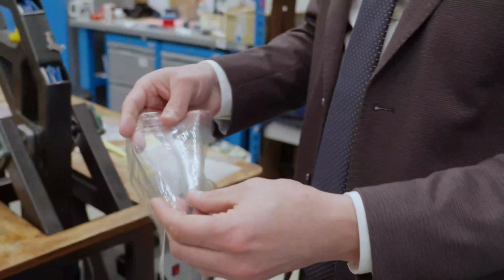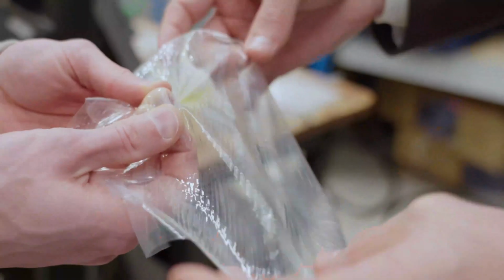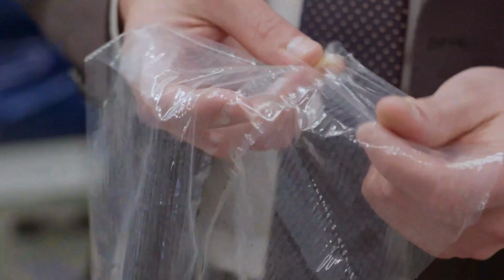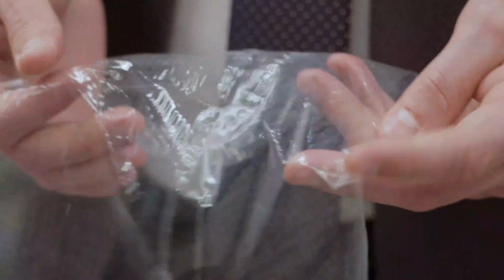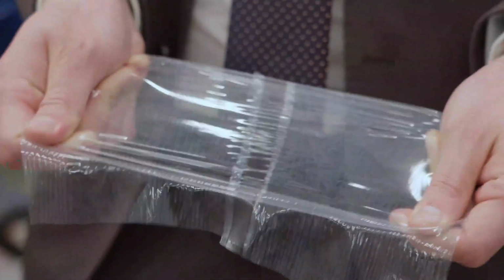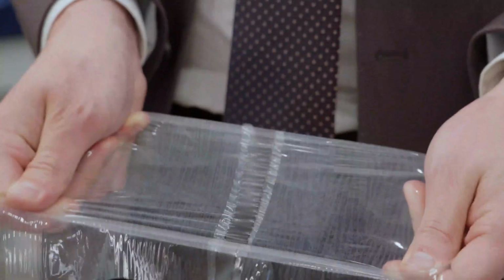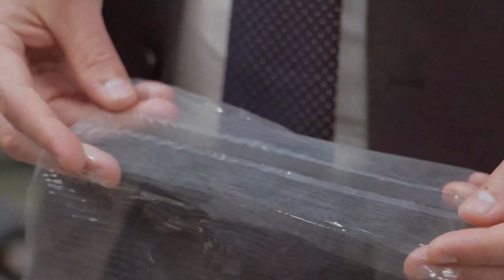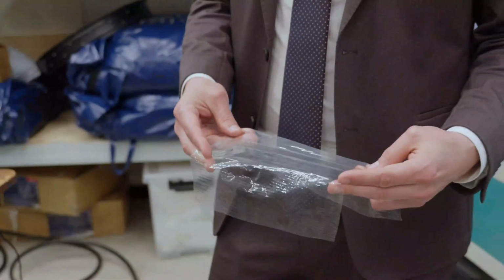Here's a neat little seam, very soft. This is a 50 micron film. At the seam and material boundary, no defects form even under significant loads. That is, all of this is important to us, not just in terms of strength, but also in terms of gas permeability. Here we can clearly see that such significant defects do not form. You can weld complex large products with these precise seams step by step and accordingly achieve perfectly airtight joints.